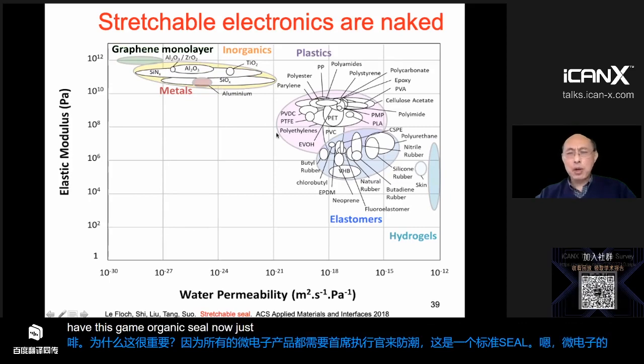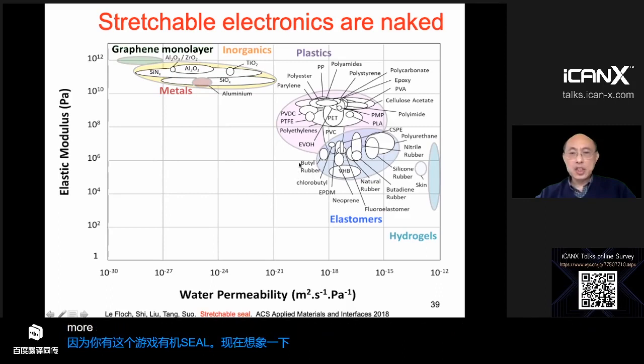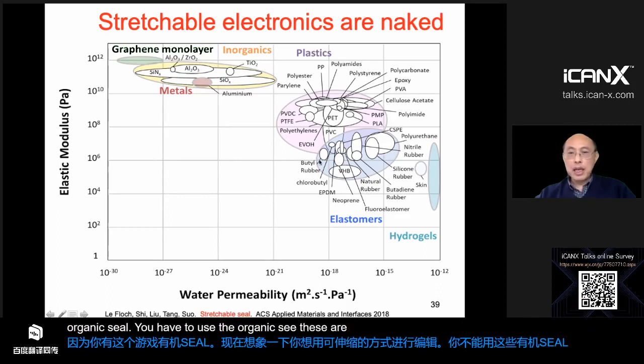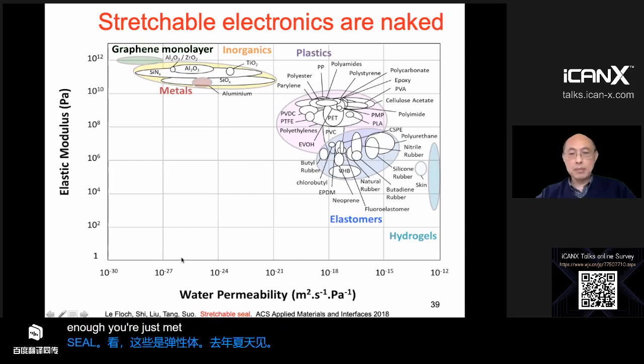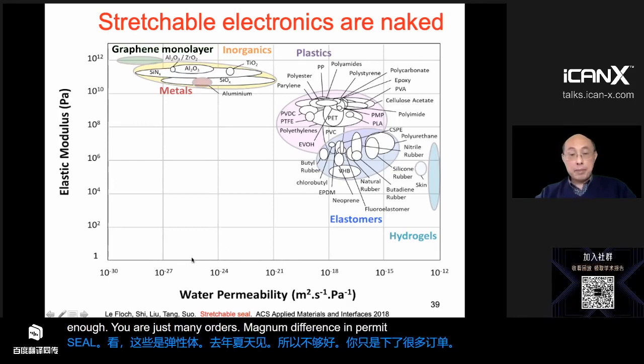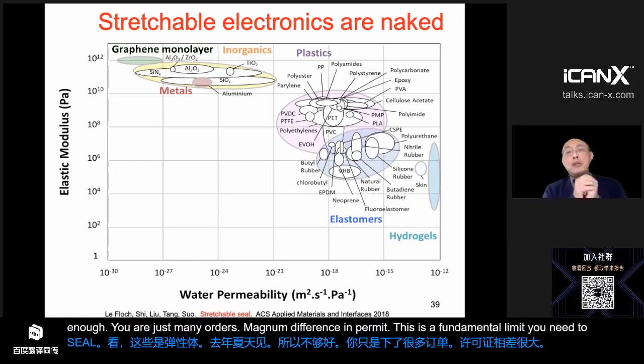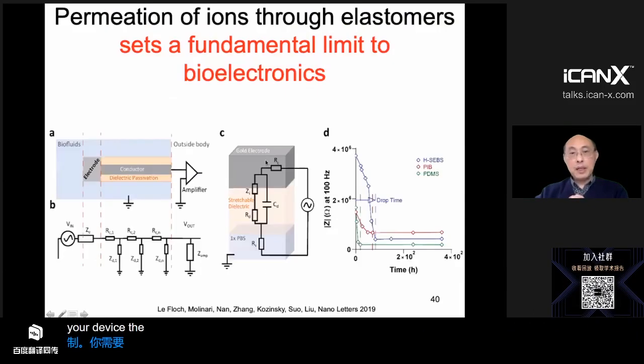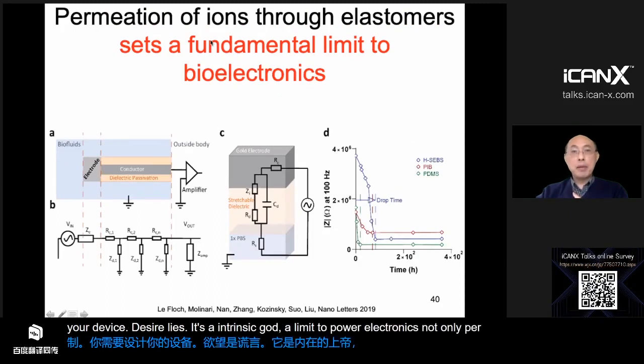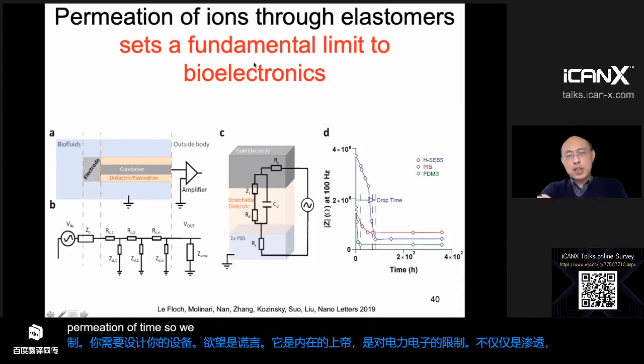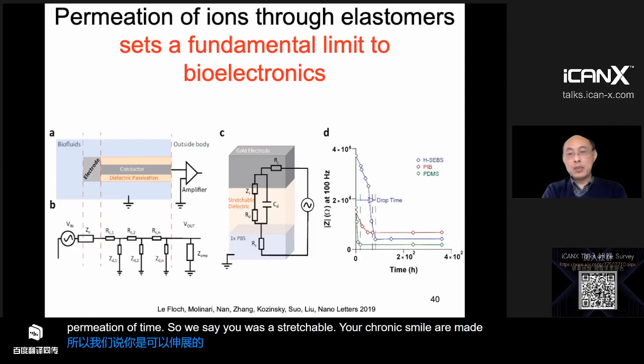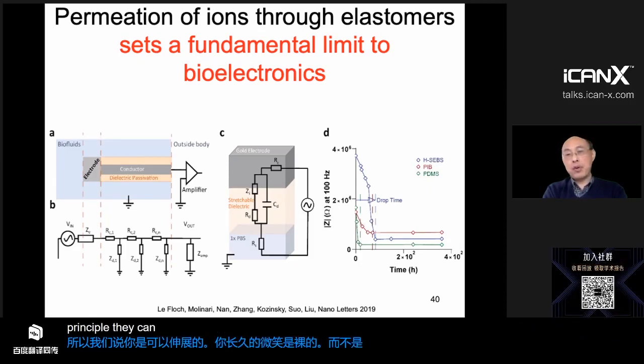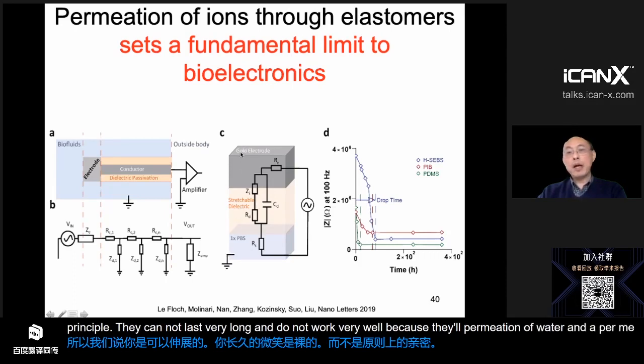Now, just imagine you want to make anything stretchable. You cannot use this inorganic seal. You have to use an organic seal, this elastomer seal. Elastomer seal is just not good enough. There are many orders of magnitude difference in permeability. This is a fundamental limit. You need to design your device accordingly. So it's an intrinsic limit to bioelectronics. Not only permeation of water, but also permeation of ions. So we say all the stretchable electronics now are naked. They do not have clothes. In principle, they cannot last very long and do not work very well because of the permeation of water and ions through the elastomer.